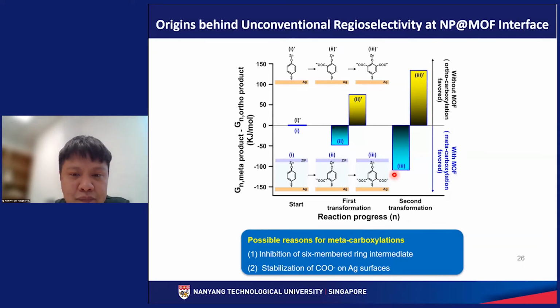So secondly, the presence of the carboxylate group very close to silver serves as an electron sink, whereby the negatively charged carboxylate group can be stabilized using the silver surface. So in any case, molecules do not want to be charged and therefore they want to interact. Okay, so that is why excess electrons from the carboxylate group can be delocalized over the silver to form a more stable product.